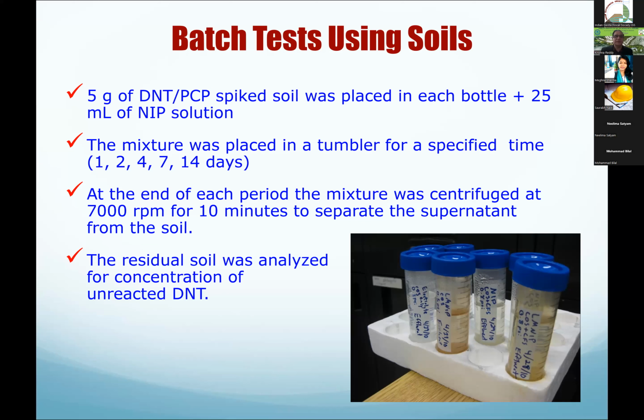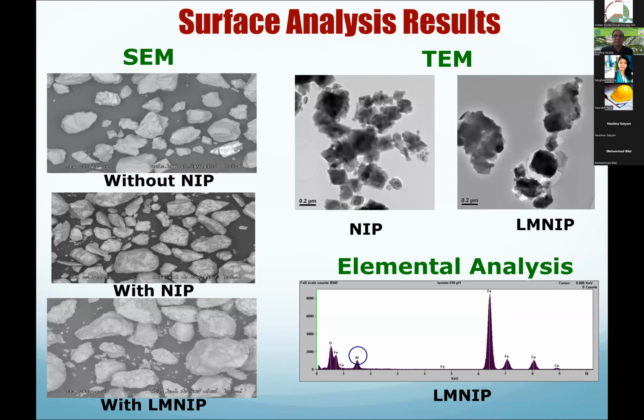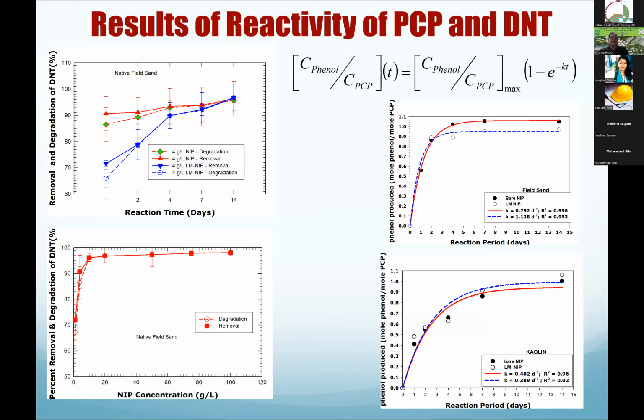Okay, so the whole idea is, are our nano iron particles reactive or not? We can always do SEM images and TEM images of these nano iron particles to look at their morphology. So here are the reactivity results. Here is the reaction time. This is DNT, I'm looking at the contaminant DNT here, and this side is the PCP. So the reaction time is, see this one, 4 grams per liter NIP, and this one, 4 grams per liter LM NIP, degradation or removal. Basically how much of the contaminant is actually remaining versus the loss.